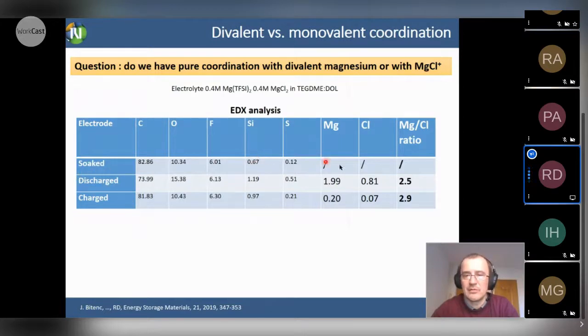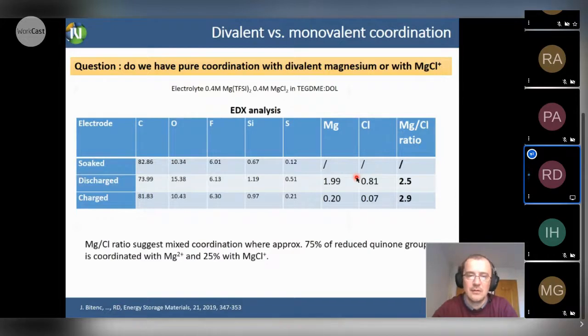we did a controlled experiment where electrodes were only soaked into electrolyte, and after washing we don't find any magnesium chloride inside. But once they are discharged, you can see that the magnesium ratio, this is weight ratio, is much higher than chloride, but still that gives us some hint that chloride is also co-inserted, and that we have some monovalent coordination with the monovalent magnesium chloride. And using some calculations, we can guess that approximately 75% of reduced quinone groups are coordinated with divalent magnesium, and 25% of groups are coordinated with monovalent magnesium.